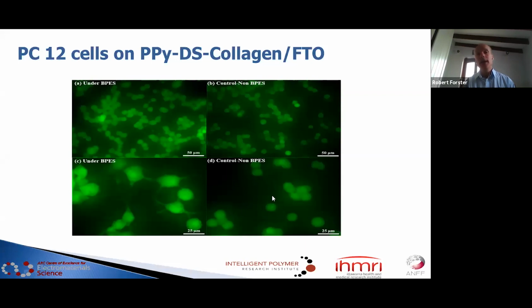Then what Chunyan does is electrically stimulate those cells, typically using maybe 1 volt between the 2 feeder electrodes. That generates about a volt potential difference in the conducting polymer, and she'll deliver that 1 volt for an hour a day for 7 days.